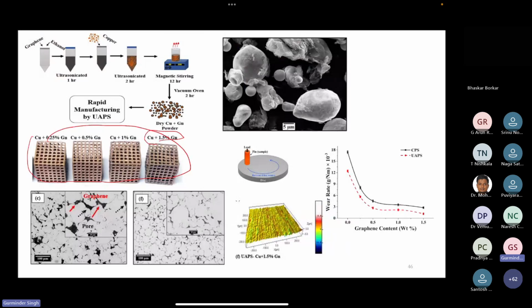If we are using the conventional process, where you are not providing ultrasonic vibration, you will have lumps of graphene. But when we are providing ultrasonic vibration, with a vibration amplitude of around 20 micron, you have your graphene at the surface of your copper particles. It gives you homogeneous mixing, and your graphene is distributed among all the particles and can easily give you better connectivity and a better channel for the mechanical properties and for the electrical properties also.